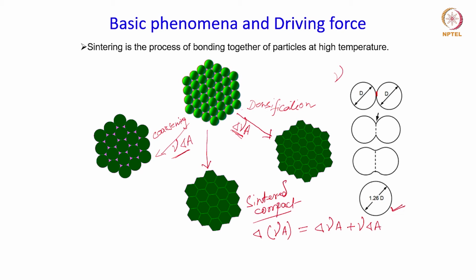Right? So this phenomena that takes place during the sintering process basically leads to a decrease in the total surface energy of the system, and that is what drives the process. Okay. So therefore we can say that the driving force for the sintering process is the reduction in total surface energy. Okay.